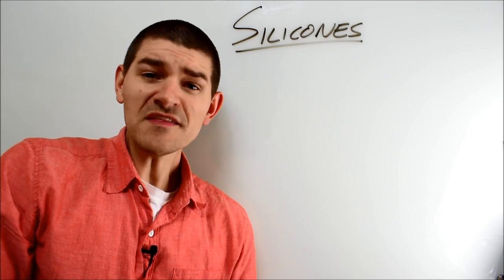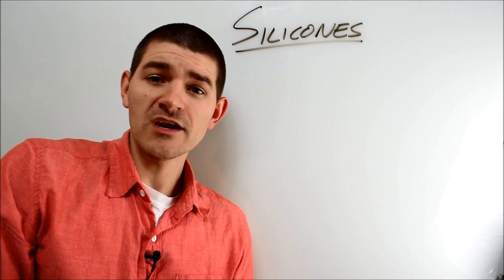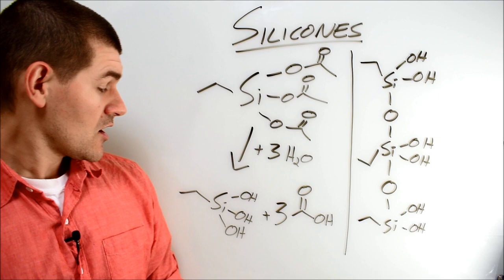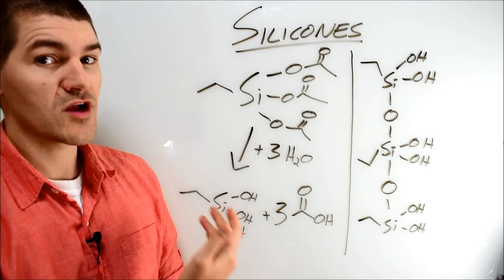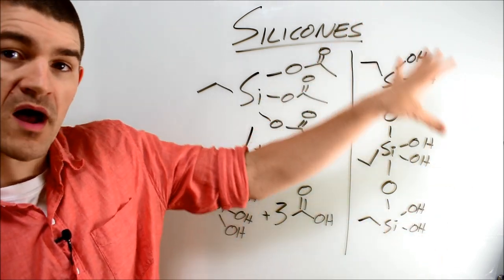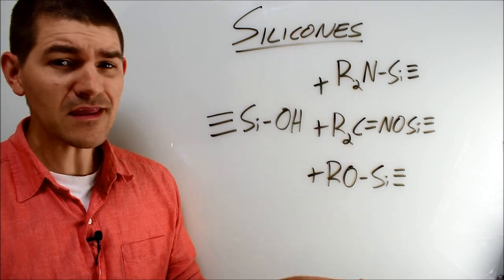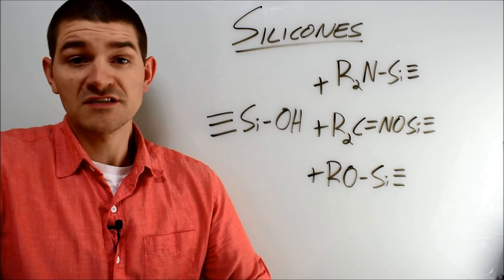Finally, let's talk about silicones — a completely different type of chemistry. Silicones deal with the element silicon. The general idea is there's a monomer that reacts to create a polymer and something is relieved in the process. Take for instance ethyl triacetoxysilane — when hydrolyzed during moisture cure, we end up with a trifunctional silanol and three molecules of acetic acid evolved. Then you can take a number of these trifunctional silanol molecules, do a condensation reaction relieving water, and get the repeating Si-O-Si-O siloxane functionality in an overall polymeric molecule called a silicone. If you don't want that acidic smell, simply react with a neutral silane such as an ether or an oxime. If for some reason you want a fishy smell, you can react with an aminosilane. Any of the bunch, the same mechanism applies, giving you a repeating siloxane polymer that can be used as an adhesive, or what most silicones are used for — a sealant.